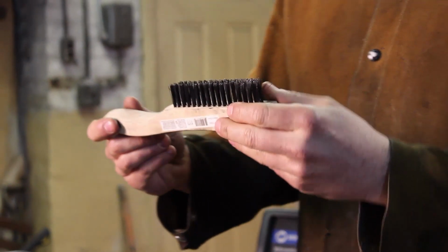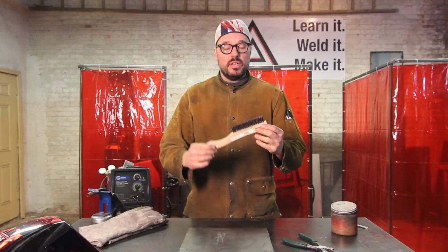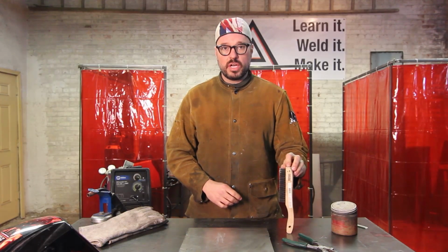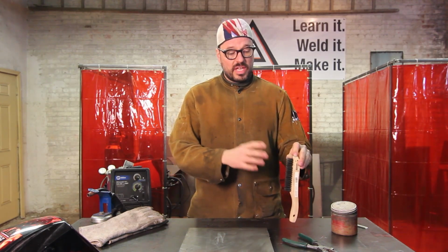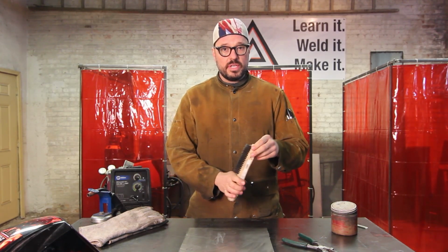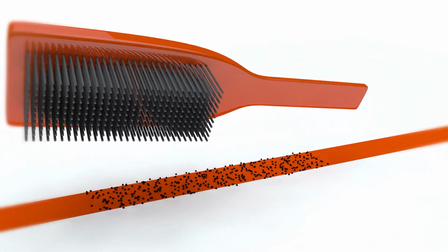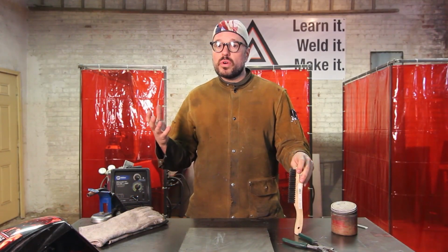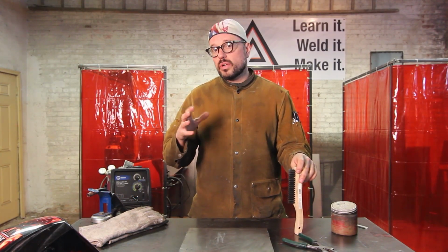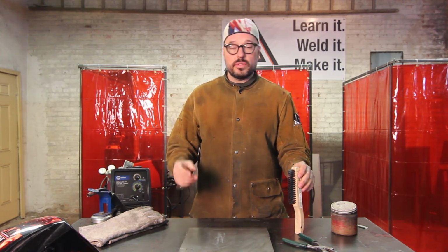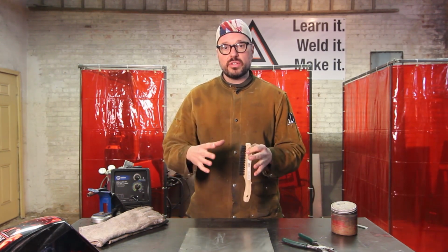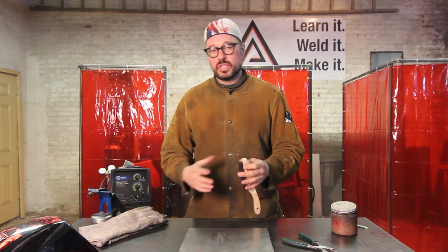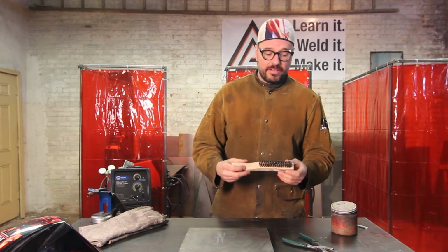Now here's the thing, I said for all of your metal products, if you take a carbon steel brush and then you use that brush for aluminum, you're going to contaminate your aluminum weld zone. You're gonna have little particulates of steel dust in there. Steel melts around 2400 degrees. Aluminum melts around 1200 to 1400 degrees. Guess what's gonna happen? Those little steel particulates are just gonna hunker down in your weld zone and they're not gonna go anywhere. They're just gonna create a big pocket and you're gonna have a bad day. So stainless steel, keep them all separate, all right? And that is your brush.